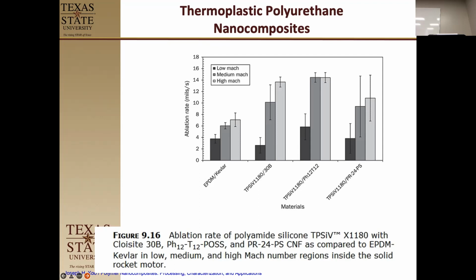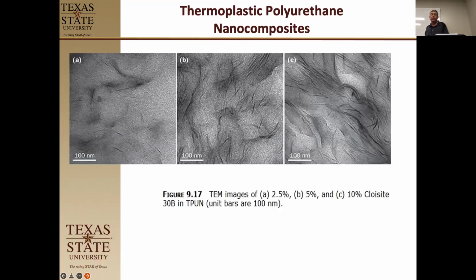That is a POSS. This is carbon nanofibers. Okay, so the results are that yes, we came up with something, but it didn't work as well. But they did show that they got the POSS dispersed in there really, really well. These are at different concentrations, 2.5 to 10%. Getting some bundling, but pretty good exfoliation, especially in that 2.5. There's almost no bundling at all.